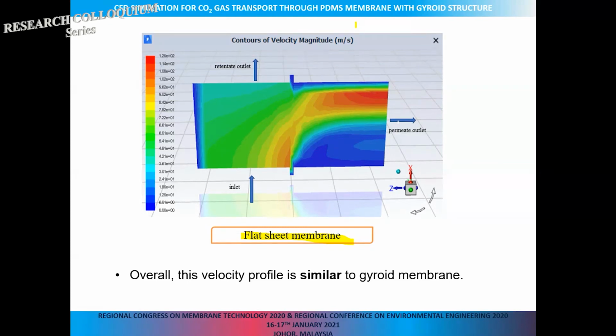We also suspect that when the gas flows from the inlet to the outlet, there is lower time for the permeation here. So as a result, they will have a higher permeation rate to pass through the membrane. And as a result, you will see a higher velocity at the outlet zone.